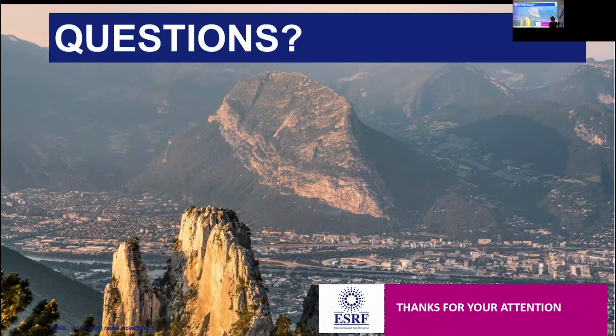Thank you very much for the very pedagogical talk. I have a question regarding when you show in some of your slides the dependence on the incident energy of the different excitations. You see that there is a fluorescence-like signal in the charge transfer region, yes, but also I observed that there is a fluorescence line in the region of DD transitions, right, between 1 and 2 electron volts. My question is, wouldn't we expect in DD transitions to have Raman-like excitations rather than fluorescence? And so what is the origin of this fluorescence-like dependence in this DD transition region?